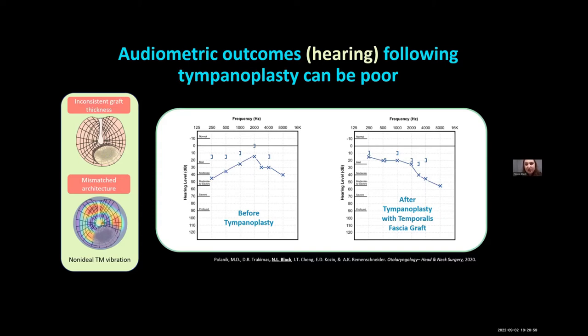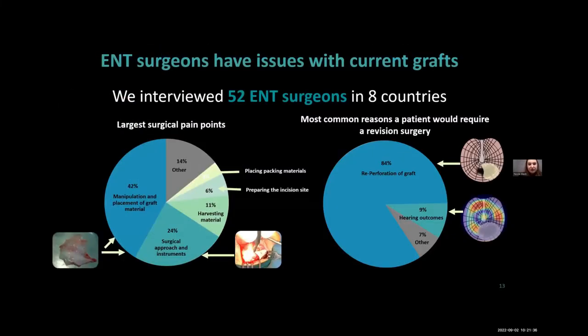So if there's a difference between where these square brackets and these X's sit for each frequency, this suggests that there's something called an air bone gap, or some form of conductive hearing loss problem in your middle ear. And so you can see for this patient, for example, before tympanoplasty, they had a pretty significant air bone gap at most frequencies that tended to close after tympanoplasty, especially at lower frequencies. However, at higher frequencies, even after tympanoplasty, starting at around 3000 hertz and then 4000 hertz, this air bone gap persists. And in some cases, this high frequency hearing might not go away. And so the reason for this really could be this mismatch in properties of these materials.